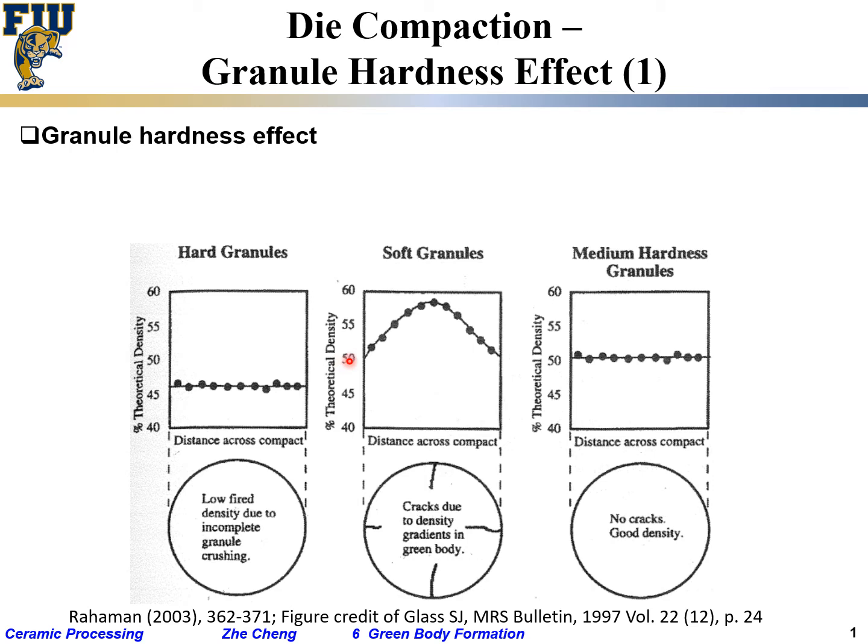Why? Because locally you've got friction between the powder and the wall, and that causes locally less of that force. Because of this non-uniform packing, quite often in sintering or even before sintering, you would have cracks. That's just the reality.